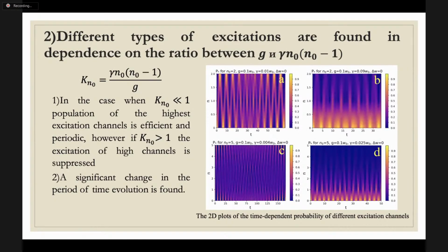Next, the existence of different regions of excitation dynamics was discovered depending on the characteristic parameter K, which actually compares the nonlinearity and strength of the interaction of the field with the electronic subsystem. And for rather low nonlinearity, when the parameter K is much less than 1, a strong coupling between the electronic subsystem and the field provides the Rabi-like dynamics of excitation and periodic efficient population of the highest excitation channels. And this fact is illustrated by two-dimensional plots of the time-dependent probability of different excitation channels presented in figures A and C for initial number of photons in the field 2 and 5 respectively.